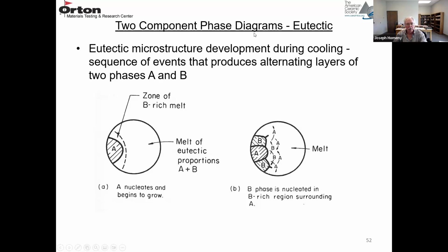So again, phase diagrams are highly useful. You know your refractory composition, you can exactly tell what happens when you heat it up. And two component phase diagrams are simple. Three component diagrams are a little more complicated. But refractory systems are more complicated in two or three phases. There's a lot of impurities. And when they're in contact with a melt of some type like a glass or a slag, you can also use phase diagrams. So the compositions get quite complicated. And that's where these thermodynamic calculations come in handy.